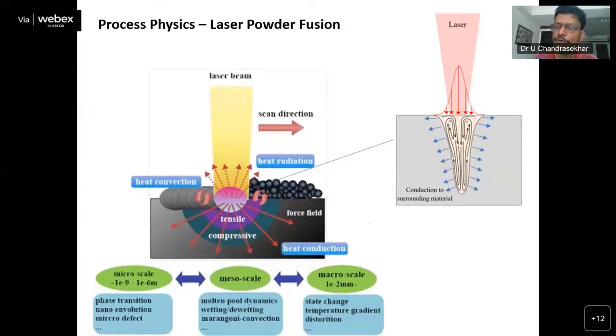You have all the three modes of heat transfer, including the radiation because of the inert gases that are available in the process platform, the convection within the melt pool, which happens because of the gradients in the surface tension leading to the Marangoni effect, and the conduction of the heat from the melt pool to the substrate. And the end effect of this kind of a complex scenario, wherein the heat transfer can happen at 10 to the power of 5 Kelvin per second, could be found at the macro scale in terms of distortions and residual stresses. It could also have immediate impact on the microstructure of the part. And last but not the least, there are the phenomena which are at the mesoscale in terms of the surface finish and inclusions because of the process.